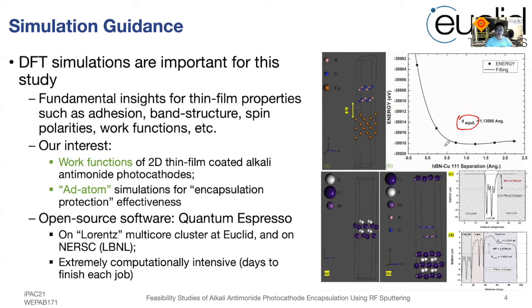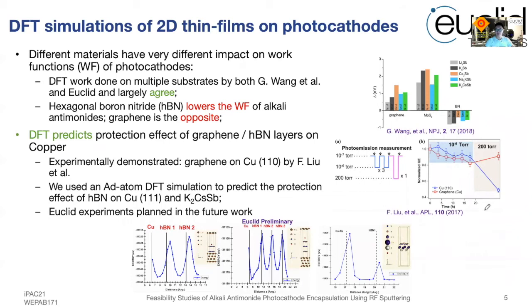And also you can see from some other simulations we did showing the work function calculation through the DFT approach. Other groups have also done DFT work, and had shown excellent and promising results for us to proceed. This includes some work published in NPJ in 2018. Our DFT simulations done independently at Euclid agreed with their published results.